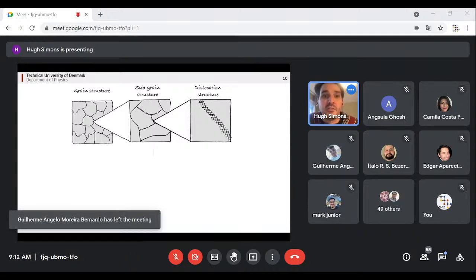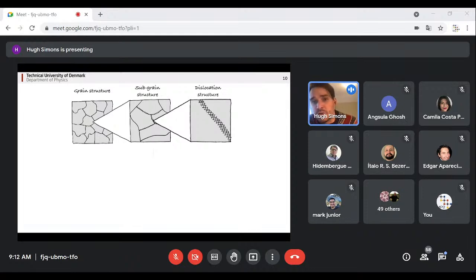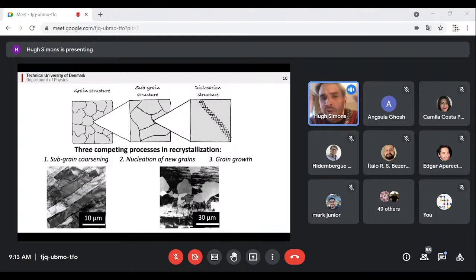So you have many of these different grains, but inside these grains you have what are called subgrains. So you essentially have regions of perfect crystallinity separated by these lines of dislocations effectively. And these give very small but discrete orientation differences between the different subgrains. And the way that these subgrains interact with each other is very important for recrystallization.